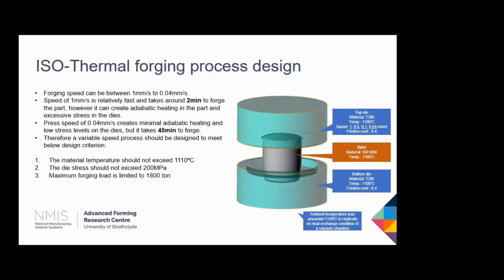The problem with 2 minutes, though, is that there's significant adiabatic heating. Even at 1 millimetre a second, there's still significant adiabatic heating, particularly in super high strength alloys such as nickel powder alloys. So we need to make sure that in this case, we start forging at 1,100 degrees, but we can't go any higher than 1,110 degrees. Otherwise, there'd be some technical problems. So the material should not exceed 1,110 degrees. The die stress should not exceed 200 megapascals. We really have to keep the stress down on the dies, otherwise we're going to have very low die life. And the maximum forging load, because of the capability of our machine, can't be more than 1,800 tonnes.